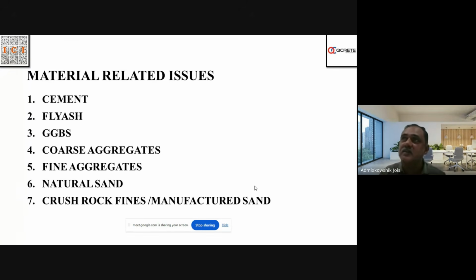So for fly ash, ready-mix concrete producers or any concrete producers will do the fineness test, and the surface area is very important. The reactivity, pozzolanic reactivity and the effectiveness of fly ash depend on the surface area. So the 45 micron test is done, and retention should be not more than 34% when it is sieved on a 45 micron sieve. For GGBS, it is 20%. And the glassy material, which is Al2O3, SiO2, Fe2O3 and CaO, both in fly ash and GGBS, will vary.